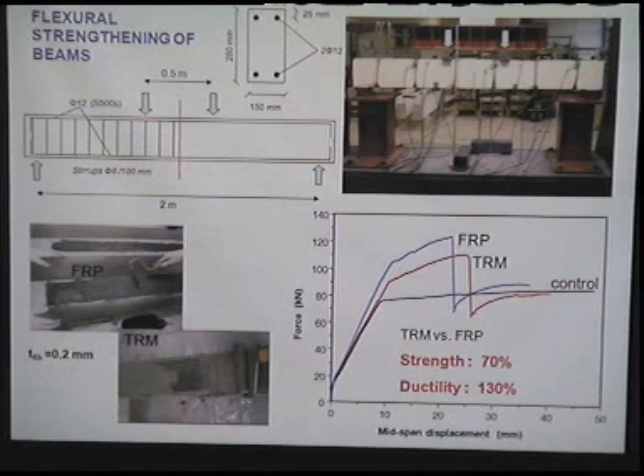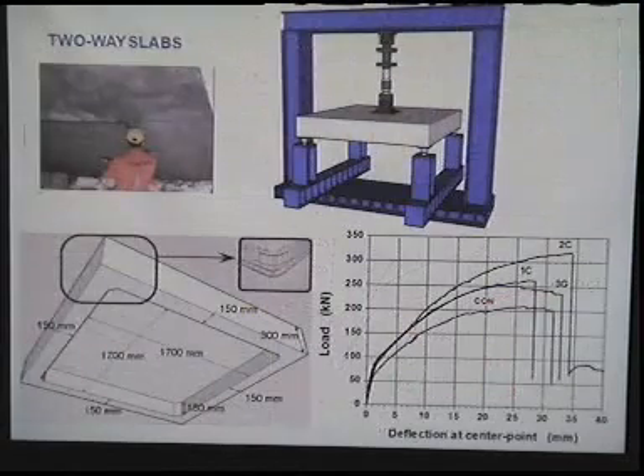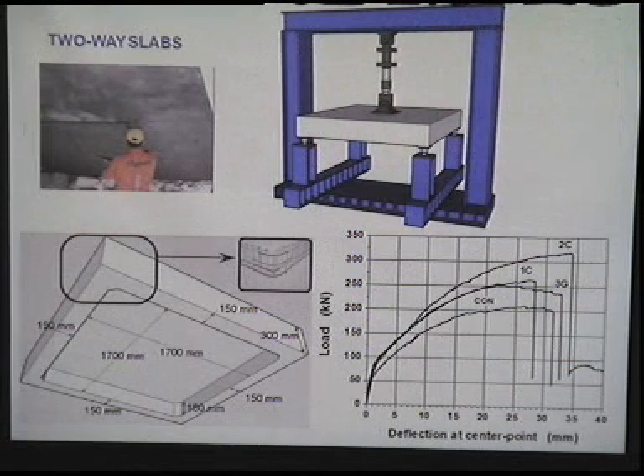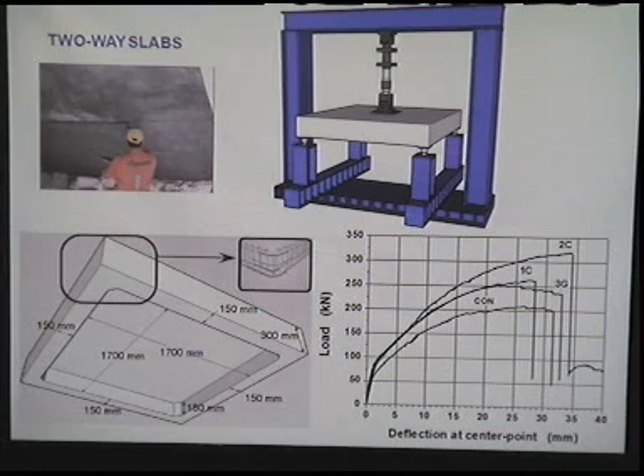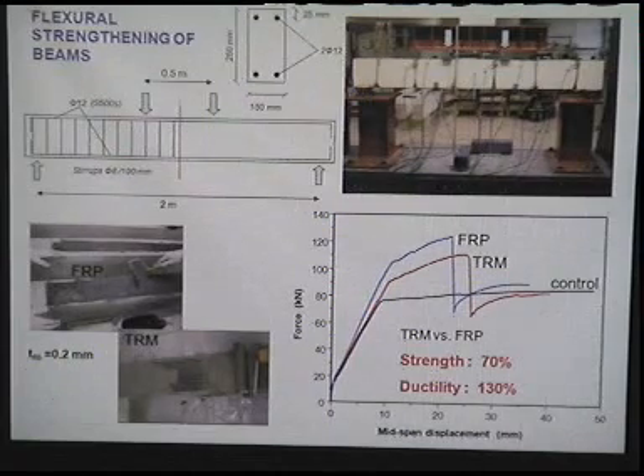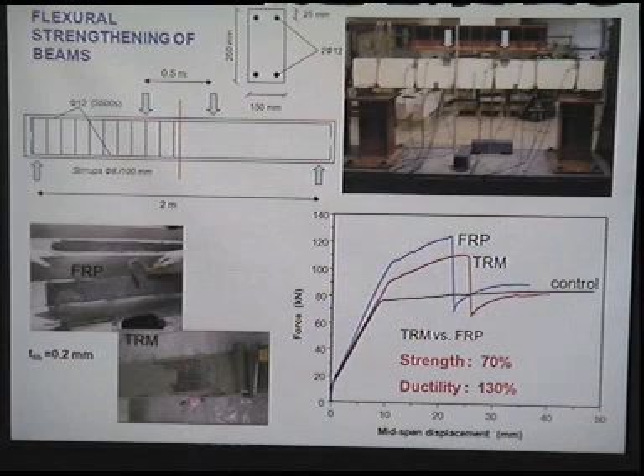So we have an increasing capacity, but not as high perhaps as in the case of FRPs, but we also have an increase in deformation, in ductility, if we compare the system with the FRP system. Flexural strengthening of beams with those textiles is probably not a very good idea because we don't utilize the fibers in the transverse direction, so we have to use a hybrid system here.